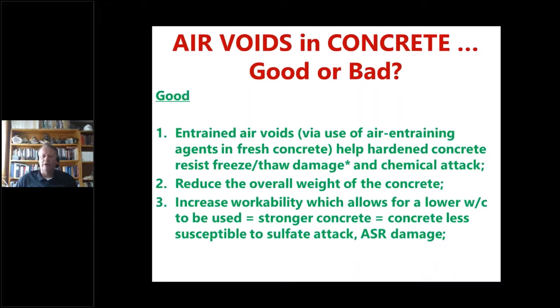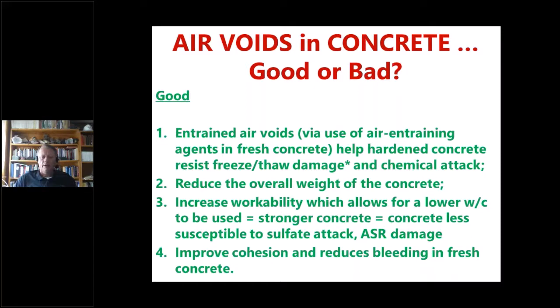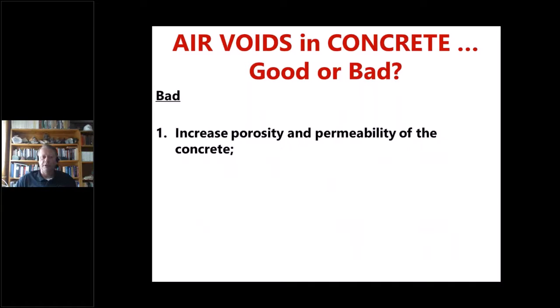And a lower water cement ratio is good because A, it makes the concrete stronger, and B, it makes it less susceptible to sulfate attack or alkali silica reaction damage. And number 4, air voids in concrete, again, improve cohesion and overall reduces bleeding in the fresh concrete. So those are the good aspects of air voids in the concrete.